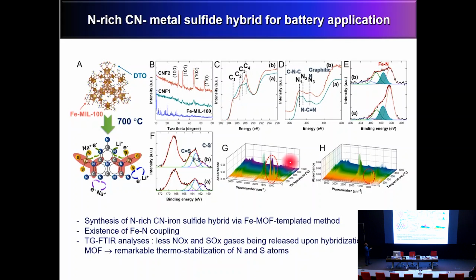We use dithiooxamide and combine it with the iron MIL-100. This iron reacts with the sulfur from the dithiooxamide to give iron sulfide nanostructures, and the dithiooxamide gives the carbon nitride. So you have iron sulfide in carbon nitride in a single system, right? Interestingly, when we put the iron sulfide into this material, the decomposition temperature increased quite significantly. That means the thermal stability of the material improved significantly. Also, the iron makes strong bonding with the nitrogen in the carbon nitride matrix.